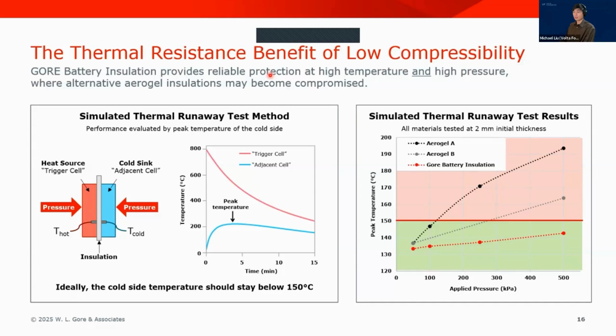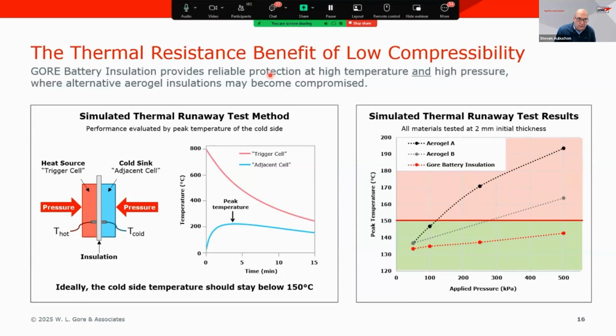Awesome. Thank you. And then Bradley Willard asked, how thin can this material be manufactured? I know that your nominal is 1 millimeter, but looking for the minimum there. That is an area that we really haven't investigated tremendously. We have produced down to about 500 micron, and in some really short runs, we've investigated producing sub 500 micron. But again, we're trying to target the sweet spot of the battery ecosystem here.